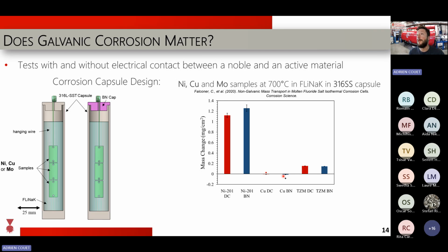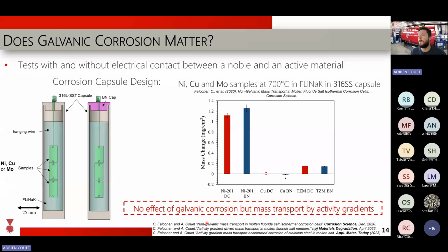So what is going on? Well, I'm not going to go into the detail of that. I invite you to read those papers at the bottom, but basically we think galvanic corrosion has no effect. It's not something that is important at those high temperatures. We think, on the other hand, that there are activity gradients between the stainless steel and the samples. And so you have a dissolution of the elements from the stainless steel in the salt, as expected. But those elements can then enter the material here if they have an activity in this material that is low enough, like chromium in nickel. There is quite a bit of solubility of chromium in nickel and iron, relative to 316 stainless steel. And so basically chromium is just being pumped by the nickel and ends up in the nickel, which leads to weight gain of that nickel.